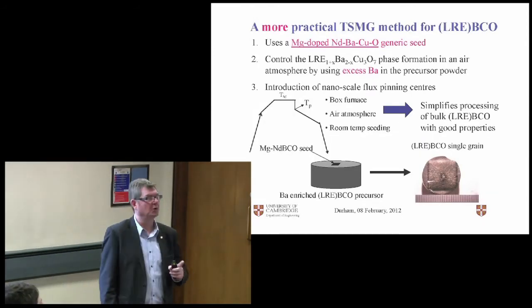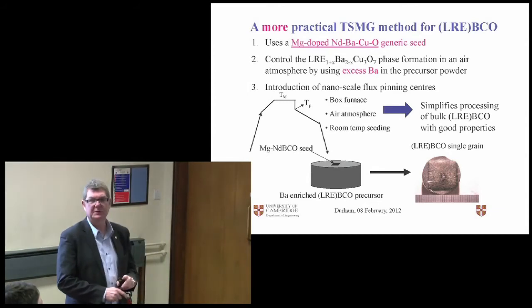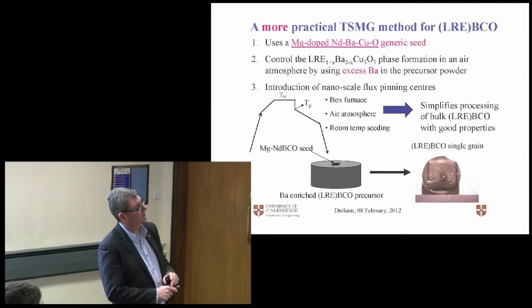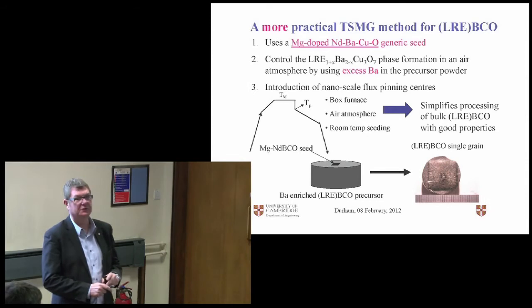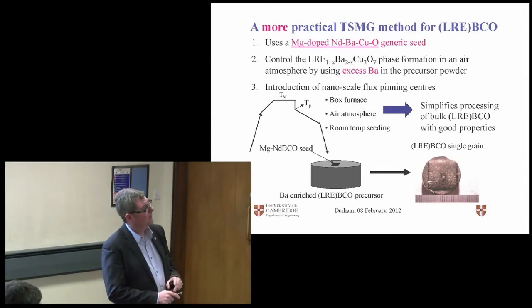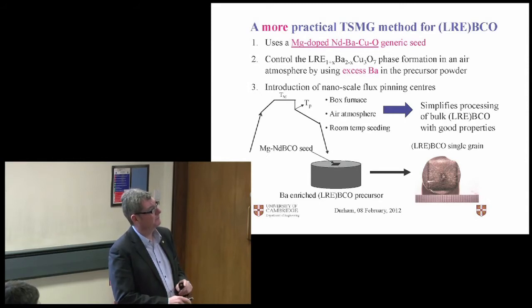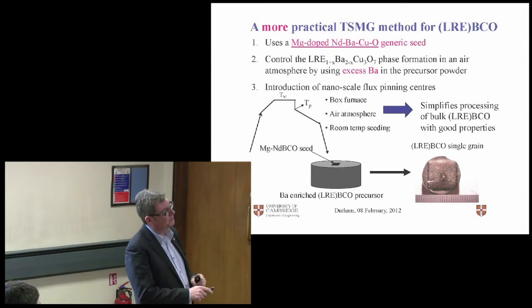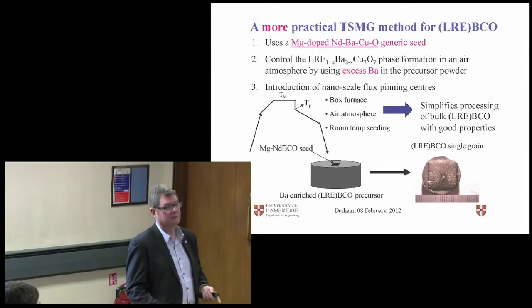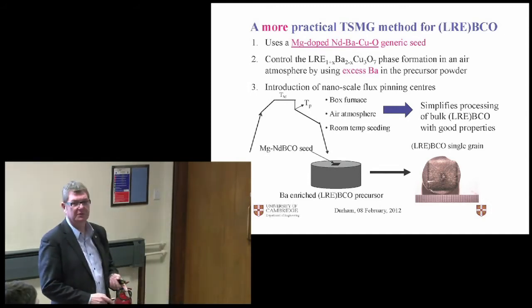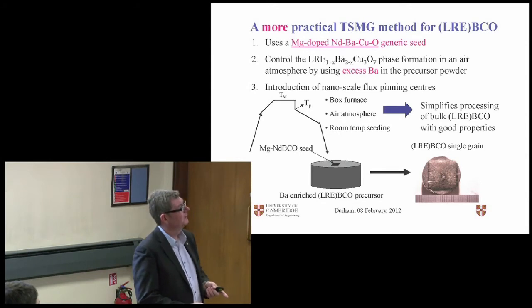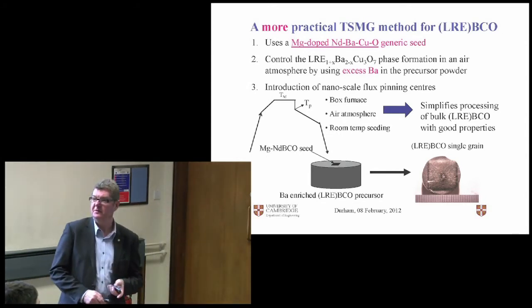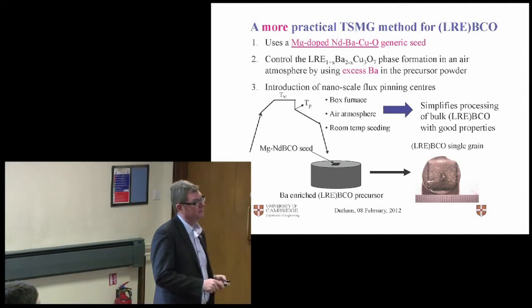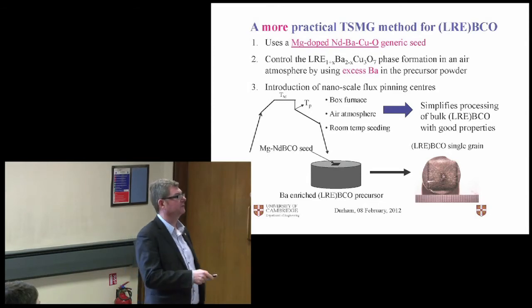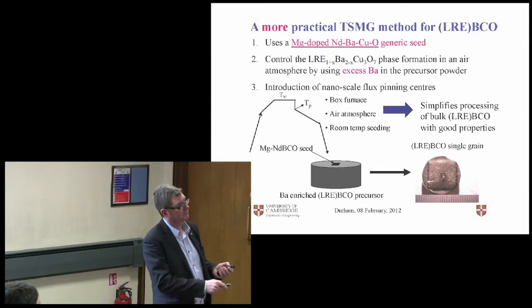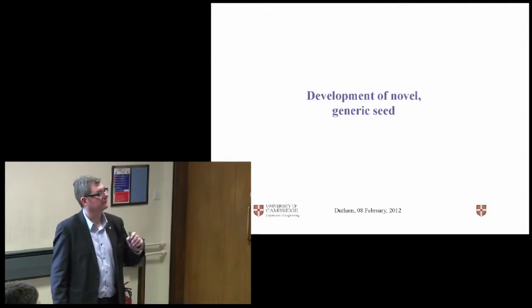So our challenge was to develop a more practical process. And the way we did it was to have 3 different influences in the processing. The first was to develop a new seed, which we could use at room temperature. The second, pretty obvious in retrospect, is that if you add excess barium to the composition, it inhibits the doping of the rare earth element onto the barium site, and you don't have to worry about a processing atmosphere. I can't believe how simple this solution was after we'd spent months and months trying to work out what to do. And the third thing is to introduce better pinning centres, much better than the 211 phase. If you do that, you can use a standard melt process in a normal furnace, add the seed at room temperature, and grow single grains. So you get a very simplified process with good properties.